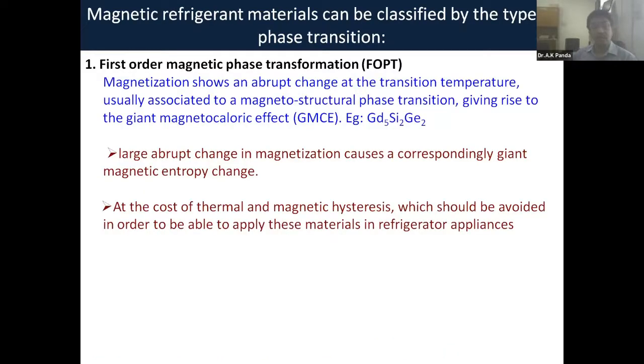So when we talk of the transformation, basically the magnetocaloric effect is related to magnetic transitions, phase transformations. And when we talk of magnetic phase transformations, a few things are very, very important. There are two types of phase transformation. One is the first order magnetic phase transformation. What you really find is that the magnetization shows an abrupt change at the transition temperature, and we sometimes call it the magnetostructural phase transition. And because of the magnetostructural phase transformation, you are able to get a giant magnetocaloric effect.